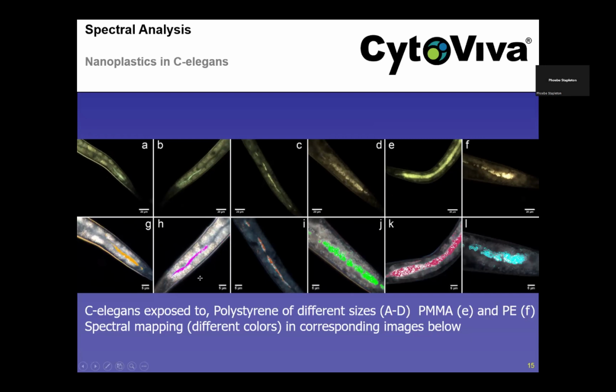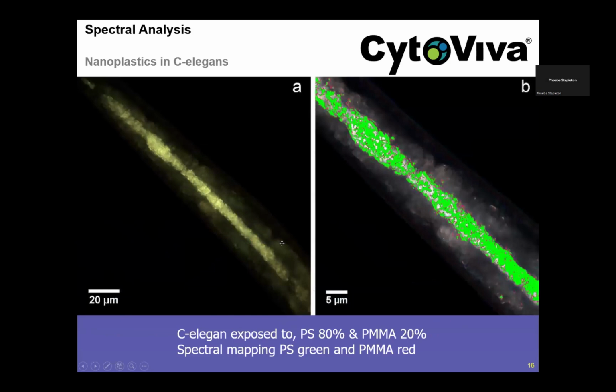And in the bottom image here, we're looking at where they spectrally mapped those polymers in the gut section of the C. elegans. And you can see here in this last image that we're looking at that you can actually see these materials, and they have a certain geometry inside the C. elegans. So there's very distinct levels of detection and discernment that were able to be determined using the instrument in this regard.